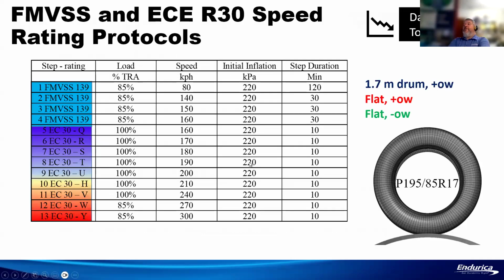So to illustrate the damage tolerant approach, I'm going to use the example of a tire. And in the tire industry, there's a government test where they assign a speed rating to the tire. And the way that works is there's a test that has 13 steps in it. So you can see each row in this table is one of the steps in the test. They start off in the first 4 steps, they run at 85% of the rated load of the tire, and they start at 80 kilometers an hour. They do that for 2 hours. Then they bump up the speed to 140 kilometers an hour for half an hour. And you can see basically in each step, they're increasing the speed on the tire. At the end of step 4, you've accumulated, what is that, 3.5 hours of tire operation at various speeds.